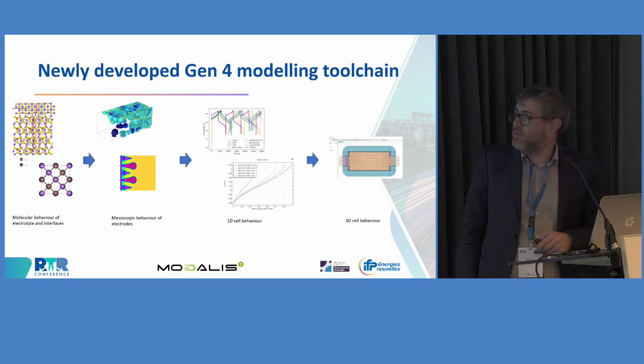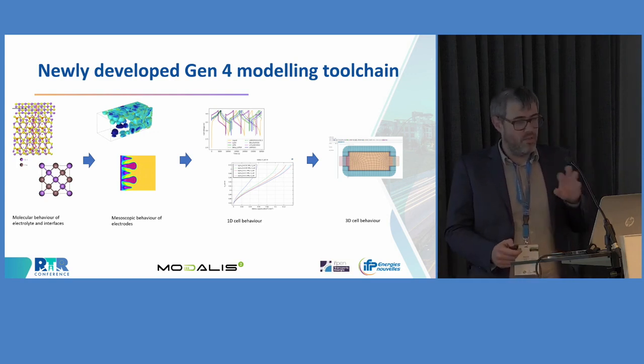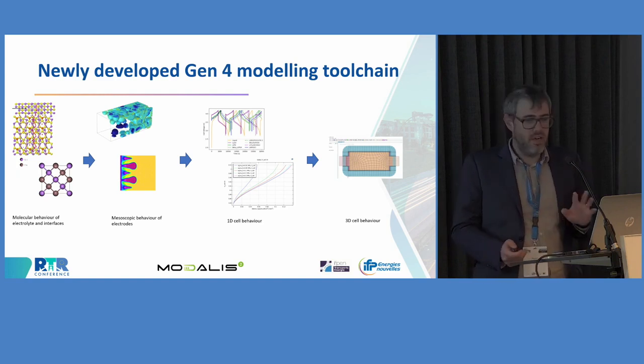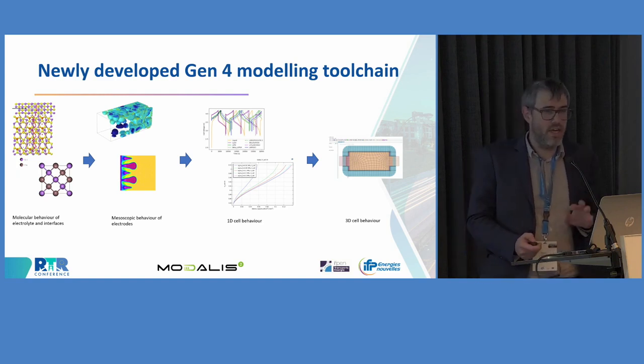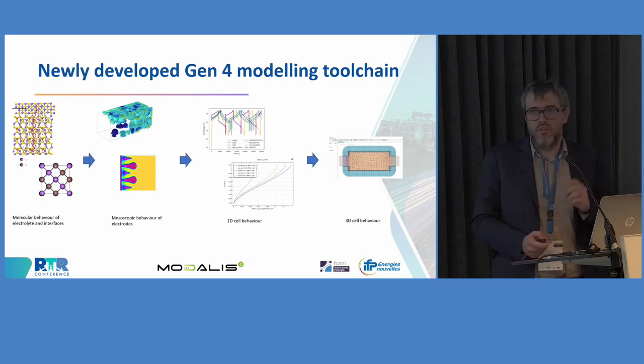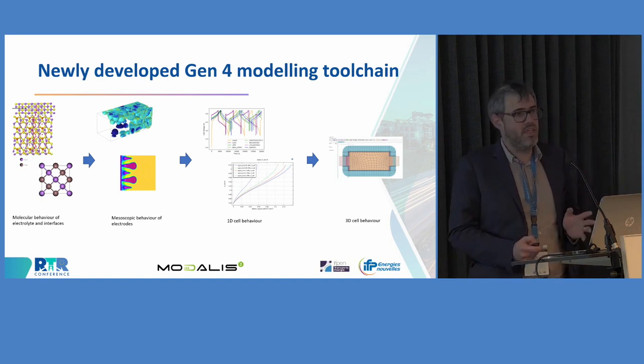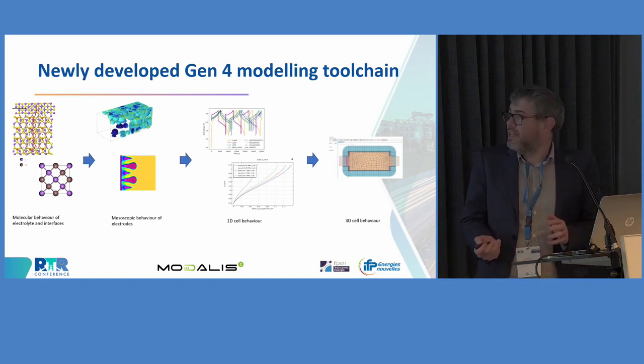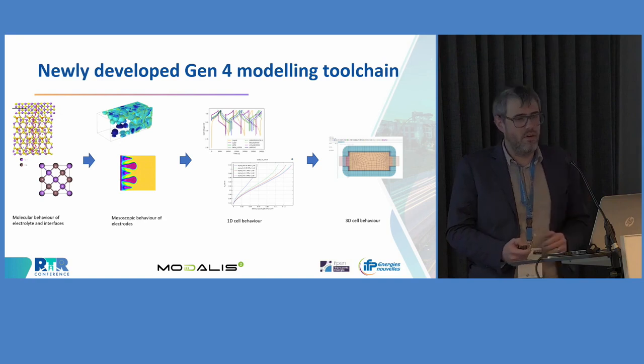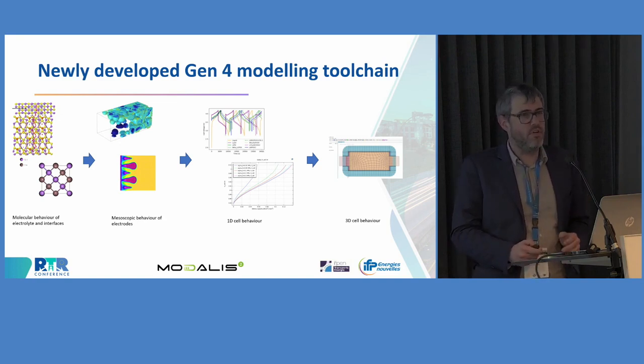Then, using 1D simulation, we wanted to evaluate the behavior of several types of solid electrolytes, and check whether the models we used for liquid ionic conductivity were still valid for solid ionic conductivity, and also implement the influence of pressure on the overvoltage in the cell.